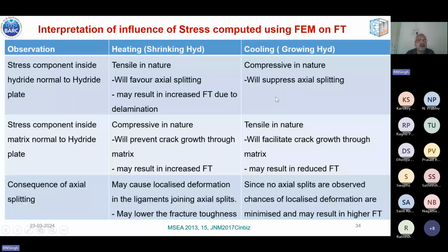A stress component inside matrix normal to hydride plate is compressive in nature for heating case. It prevents the crack growth through matrix, and may result in increased fracture toughness. However, in case of cooling, inside the matrix now it is tensile in nature, which facilitates crack growth through matrix. It may result in reduced fracture toughness.